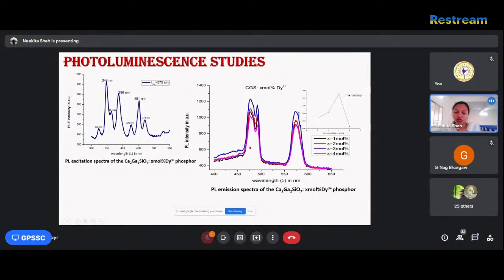The emission spectra of the prepared phosphor show two emission peaks, at 484 nanometer wavelength and the second one at 575 nanometer. The 484 nanometer emission peak arises due to the 4F9/2 to 6H15/2 transition of dysprosium ion, and the second one, the 575 nanometer wavelength emission, occurs due to the 4F9/2 to 6H13/2 transition of dysprosium ion. The intensity of the 484 nanometer wavelength is highest.